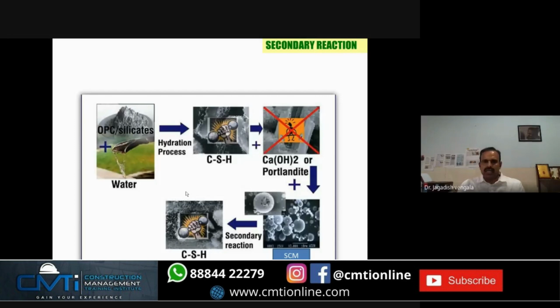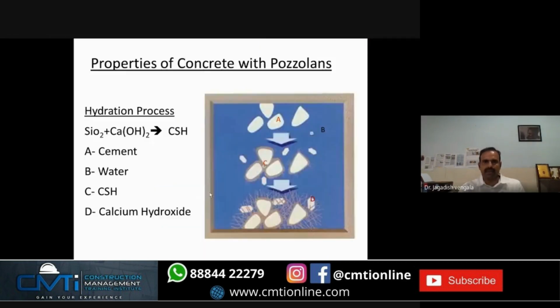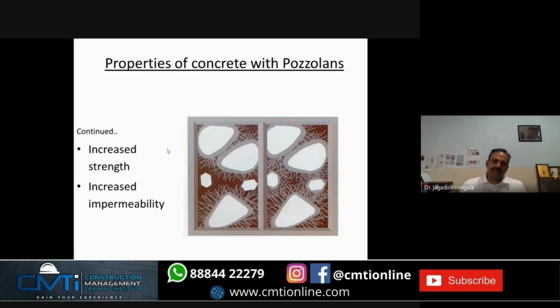to the concrete. So by adding supplementary cementitious materials in a mix, instead of 100 CSH gels, you get 120 CSH gels forming. That means more gels will form, so the concrete is denser, and you get more strength and more durability. Strength and durability are different, but when more gels form, the concrete is more durable. Anyway, this is the hydration process: silica, calcium hydroxide, CSH gel forms. Also, by adding pozzolan, it increases strength and also increases impermeability.